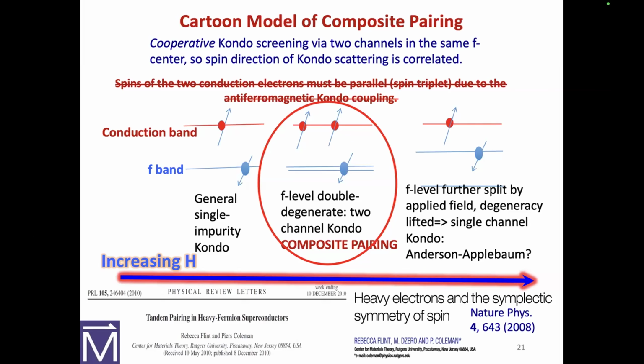So this is sort of what we're guessing here, and it probably isn't right, because when I showed you that Kondo scattering in the barrier and the linear splitting with applied field, that's looking at a single impurity Kondo in the barrier. To take it to this level has to do with me reading this paper by Rebecca Flint and Piers Coleman, and the other one with Maxim Dzero, which I've read many, many times, and I still need it explained to me. But the bottom line, getting very heuristic here, is that there's a Kramers doublet at the f level. And I have to put everything in my terms because I'm not good at computation. The f level has a Kramers doublet, so you're allowing 2 separate electrons to scatter off of that single f level.